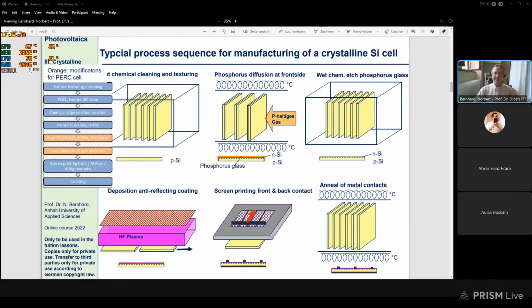Okay, in principle, you see we have here a heated tube. It could be either ohmic heating as shown here. It could also be infrared lamp heating. And then we let in a phosphorus containing gas. And this phosphorus containing gas deposits a phosphorus containing layer on the wafer, and the phosphorus starts and continues to diffuse in and to make the PN junction. So this dashed line symbolizes the PN junction. That means the initial wafer was p-doped, and that part from the front side, where the phosphorus has diffused in, becomes n-doped then. That means in this process, we have created the PN junction, which is something like the heart of the crystalline silicon solar cell.